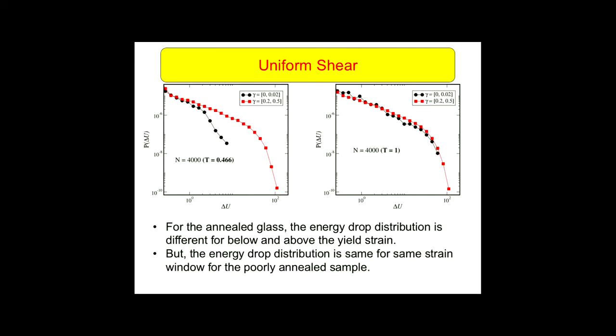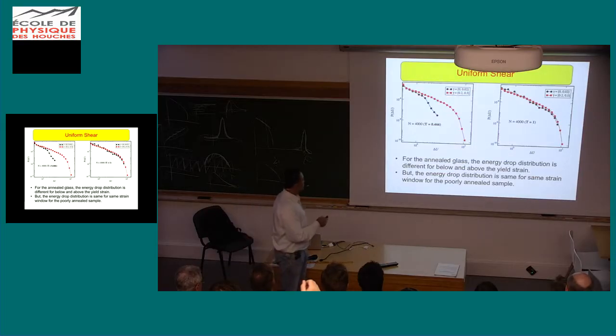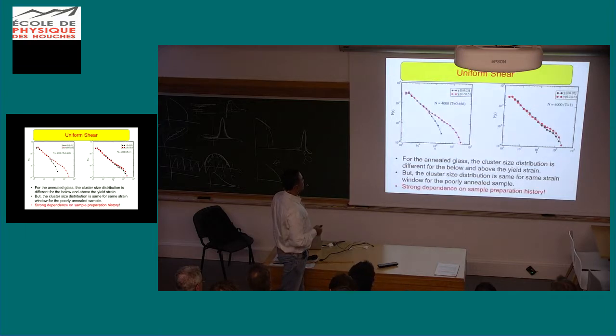In particular, for the poorly annealed glass, there isn't very much indication of where the yielding transition is, and the distributions also, in the case of a well annealed glass, look distinct between a window of strain which is small in value and a window of strain that is larger, whereas for the poorly annealed glass this is very difficult to tell apart.